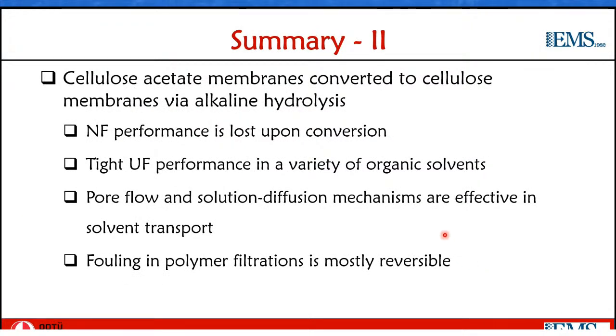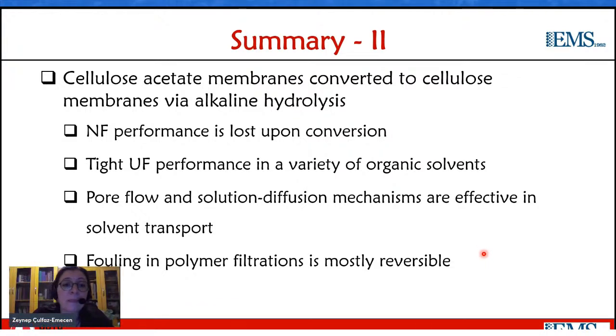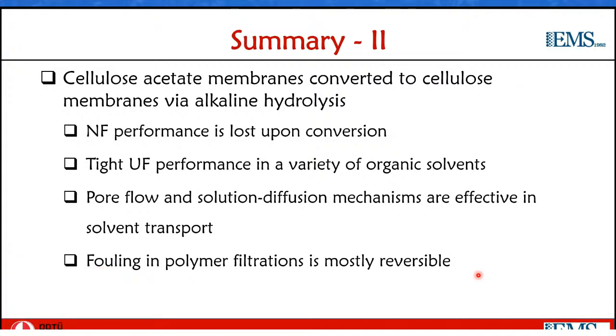So summarizing this brief second part, I've shown you fabrication of cellulose membranes by alkaline hydrolysis of cellulose acetate membranes. We observed that nanofiltration performance of cellulose acetate membranes is lost upon conversion to cellulose. However, we obtained tight UF performance in a variety of different organic solvents. It seems that pore flow and solution diffusion mechanisms are together effective in solvent transport. And fouling observed in polymer filtrations appeared to be, at least in the cases we considered, mostly reversible.